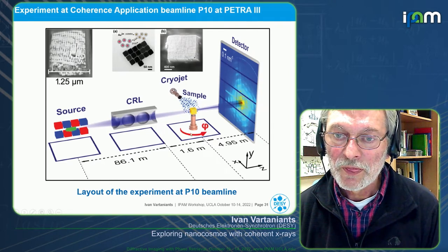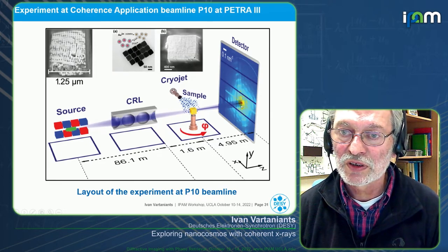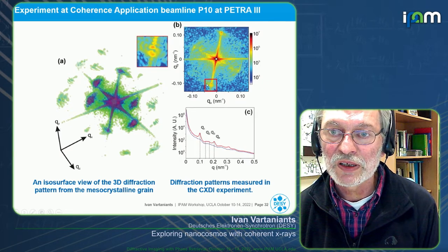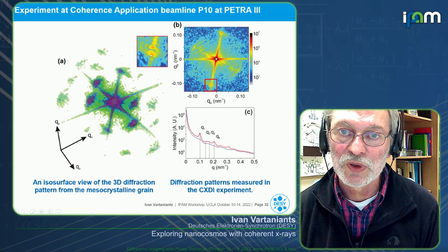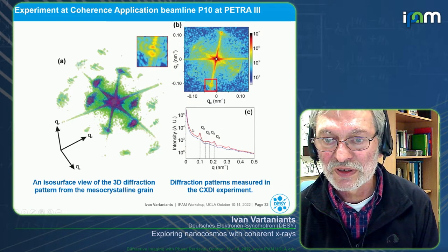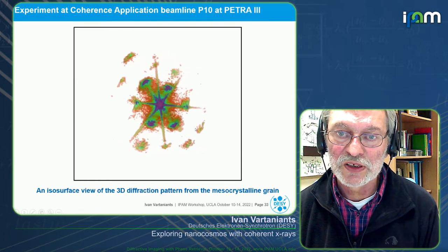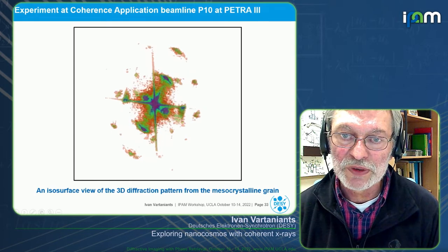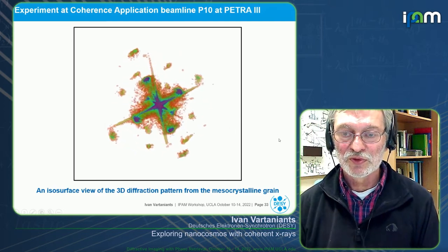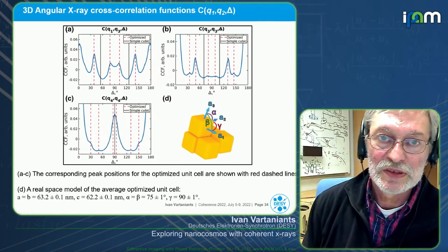We performed this experiment at PETRA III. We had the source, CRLs to focus the beam, and importantly a cryo-jet to cool the sample. We collected diffraction patterns and rotated our sample 180 degrees with 0.5-degree increments to collect data in 3D. Interestingly, some Bragg peaks were doubled, telling us there are defects. Here is the average intensity and how it looks in 3D — you could see flares due to the finite shape of the sample and quite distorted Bragg peaks, with one being a double.